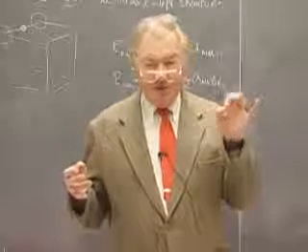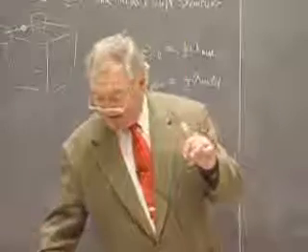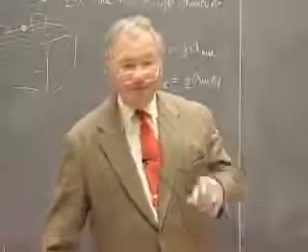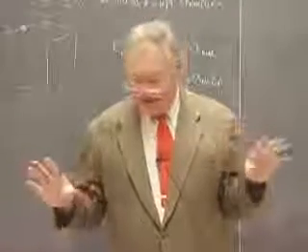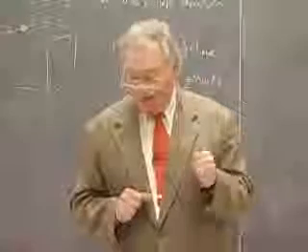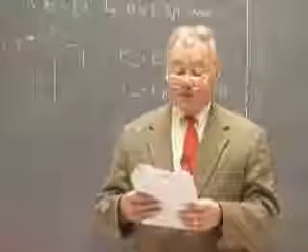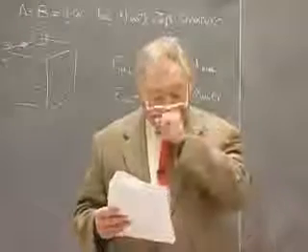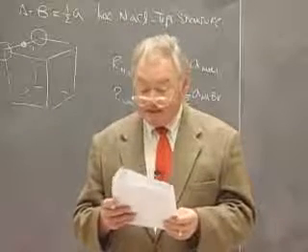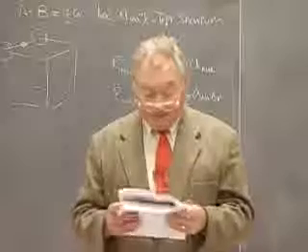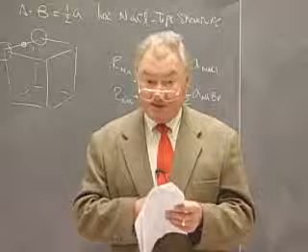And I wish I had a cookie for every half-baked book on chemistry that said, hey, Ahrens has got something for americium and Pauling doesn't. Let me put the value for americium in there. Totally wrong. They are established on different bases. So you can't mix apples and oranges. You have to use a self-consistent set of radii. The ones that were followed until very recently are Pauling's radii. And Pauling's radii are based on a standard radius for oxygen, which is 1.40 angstroms for the radius of oxygen.